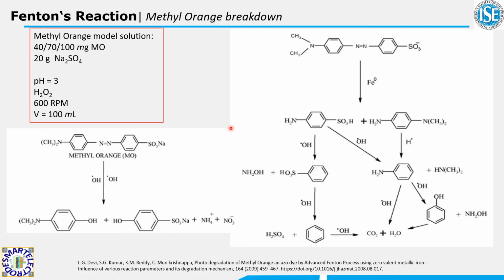As I mentioned earlier, we used methyl orange as model azo dye. We chose to use quite high concentrations of methyl orange, trying to simulate overall organic content in wastewater. Fenton's reaction or Fenton-like reactions usually are used where the TOC is around 20 milligrams per liter. We use solutions with pH 3, which was under constant agitation using a magnetic stirring bar rotating at 600 rotations per minute. Here, you can see a full scheme of methyl orange breakdown. However, the first step is the one where the methyl orange solution loses its color. Full mineralization of methyl orange occurs in at least 6 steps, requiring a lot higher amounts of hydrogen peroxide.